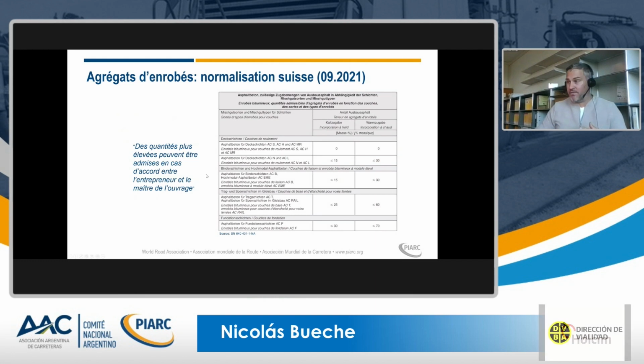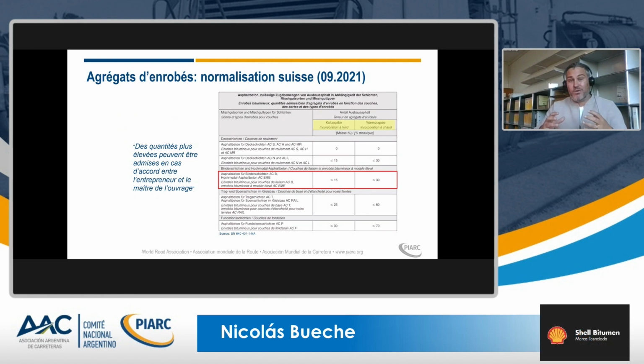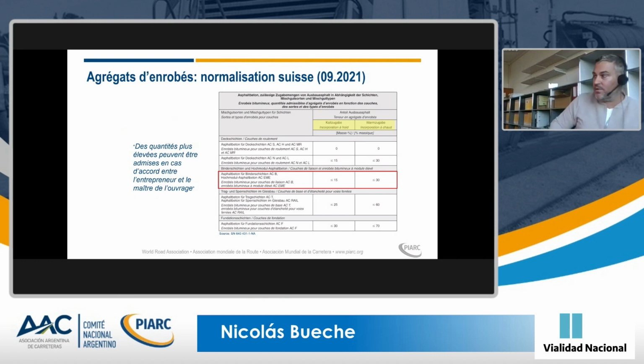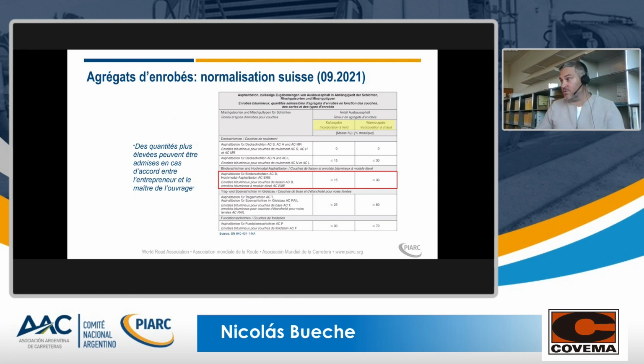This is a table that we have in our Swiss standards. Basically, in the table, we have two ways of including RAP: cold addition or hot addition. Usually we do only hot addition of RAP. This means approximately 120 degrees in the plant. And speaking about high modulus asphalt, according to the current standards, it's up to 30% RAP in high modulus asphalt. You can see for top layers with very high solicitation, we won't have that much RAP, but for the lower layers, we can go up to 60 or 70% RAP in asphalt mixture. But for today's topic, for high modulus asphalt, AMA, according to the standard we can go up to 30% reclaimed asphalt.